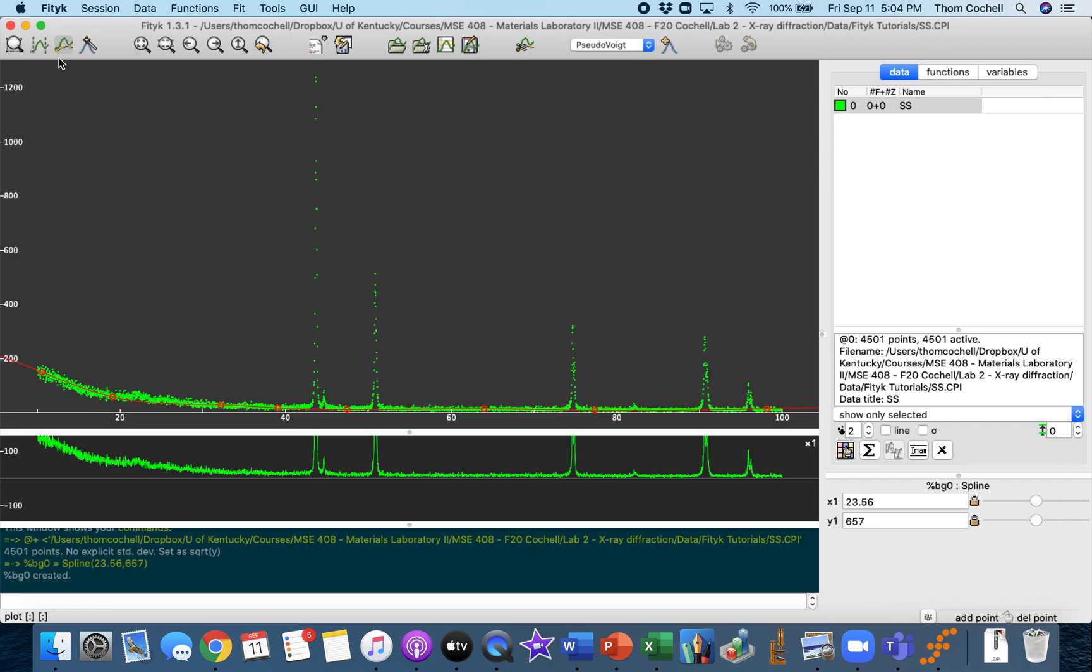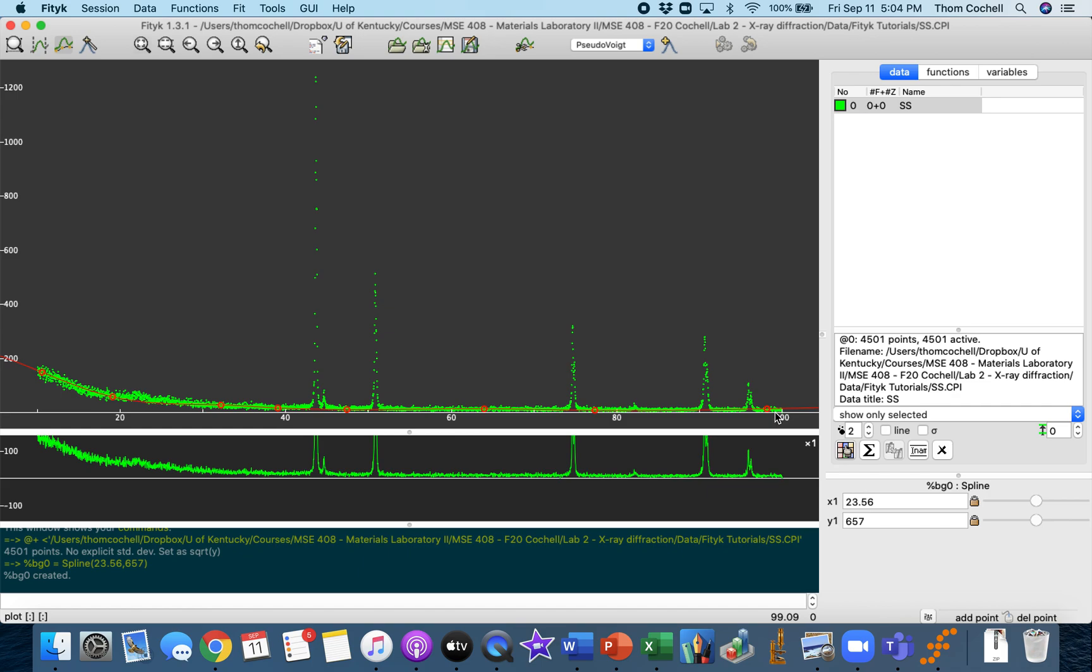We've added a few data points here. The important thing is that this red line that you see—this is our proposed baseline—matches extremely well with the green curve. You just want to kind of inspect and make sure that that does a good job of that. I try to get it in so if you see the noise and how tall this noise signal is, you want to kind of get it in the midpoint of that noise. That's kind of the idea that I'm doing with this fit. I'm fairly happy with this, so I'll use this as my baseline.